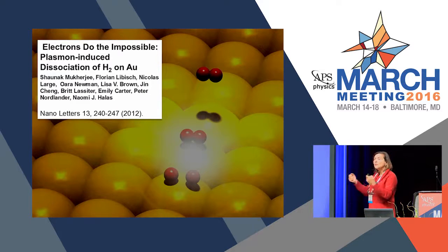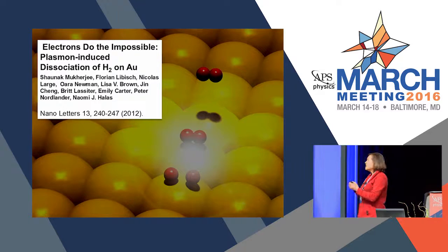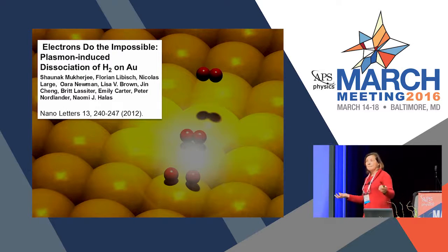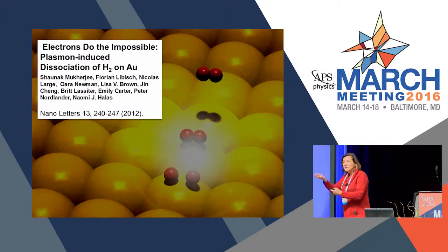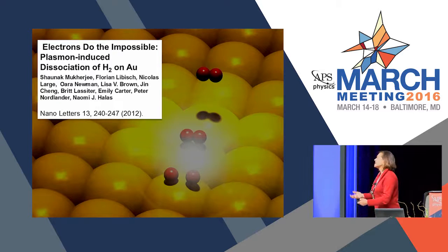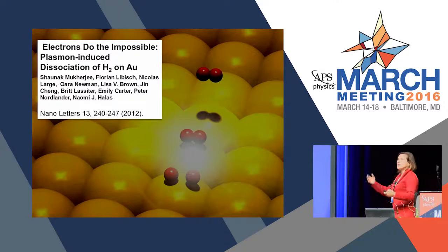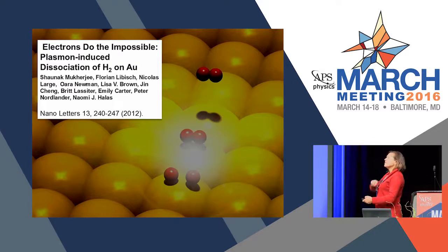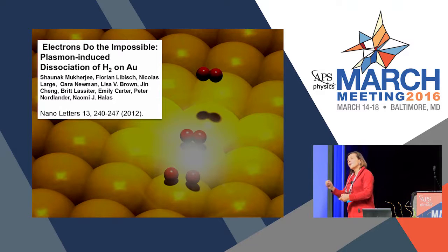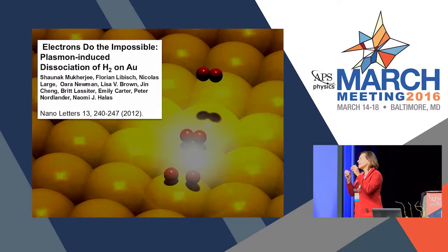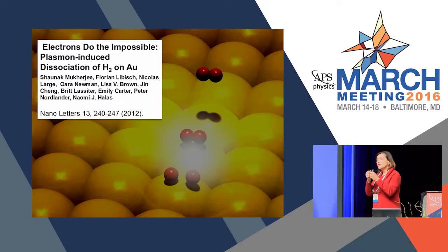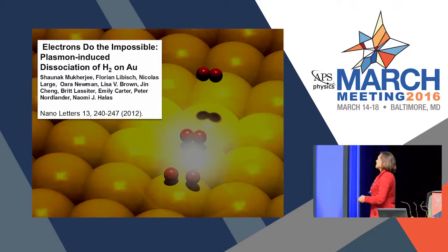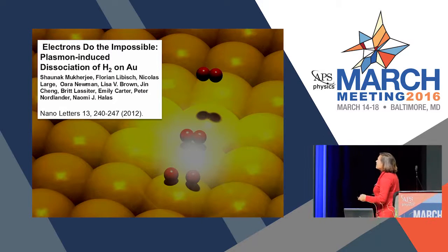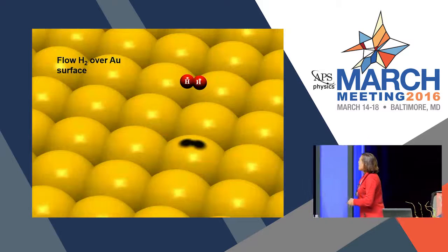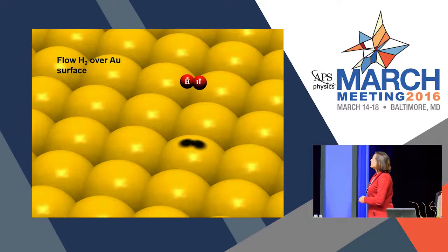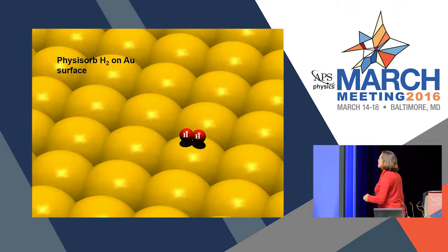So H2, the H2 molecule is like helium. Right? It won't even stick on surfaces. It is very, very inert. The dissociation energy is extremely large. But if I were to put an extra electron on that molecule, then the dissociation energy drops pretty dramatically, and it's relatively easy to dissociate. So what we do is we flow our hydrogen molecules over a surface of colloidal nanoparticles.